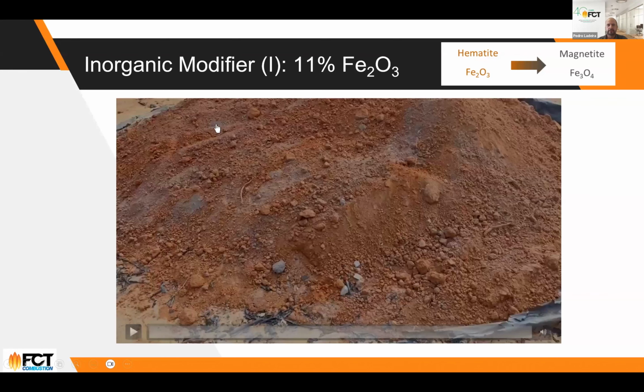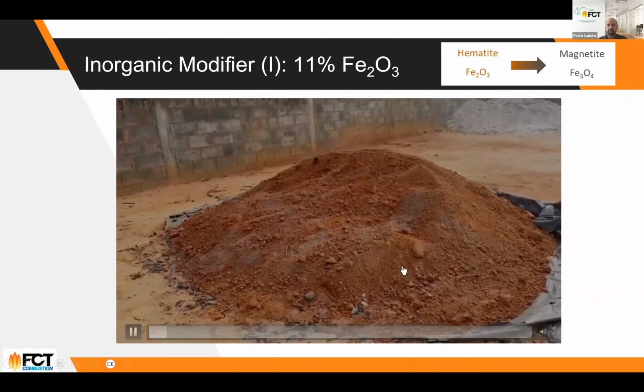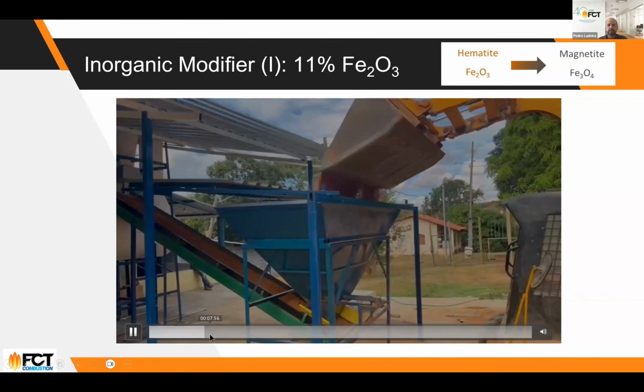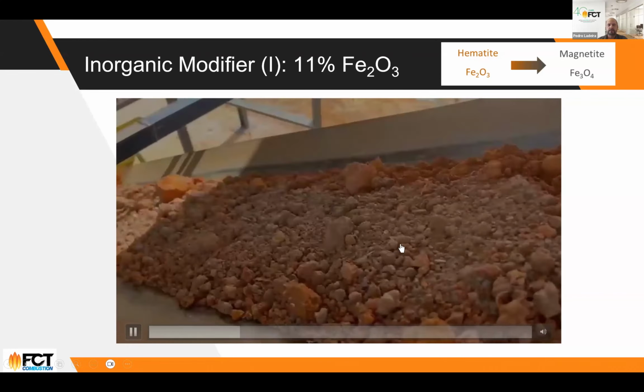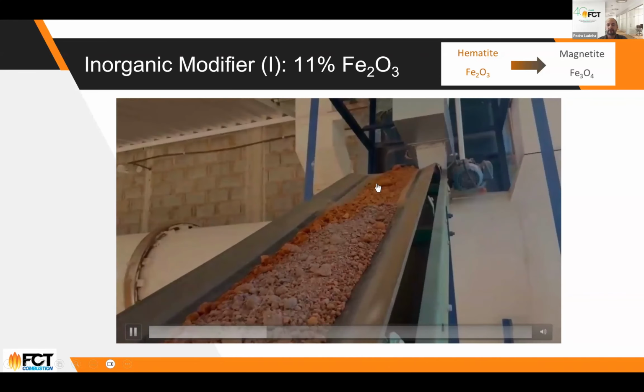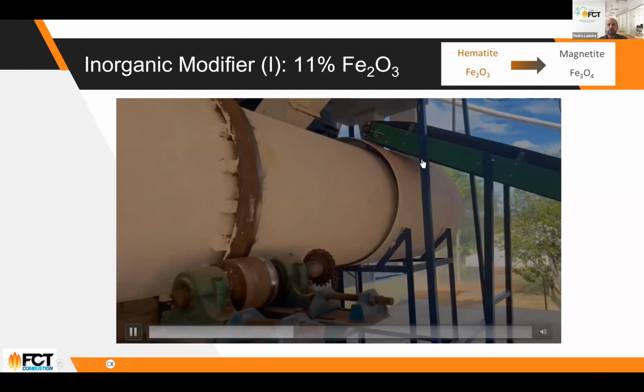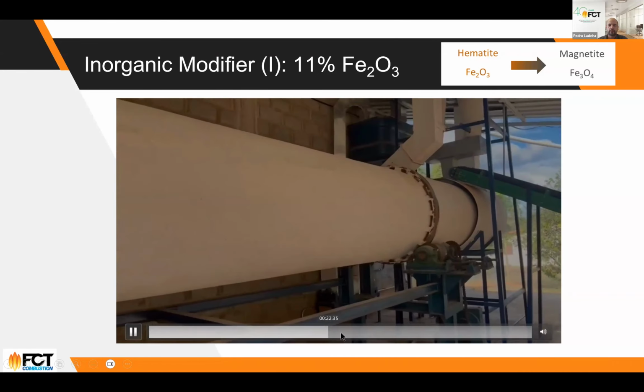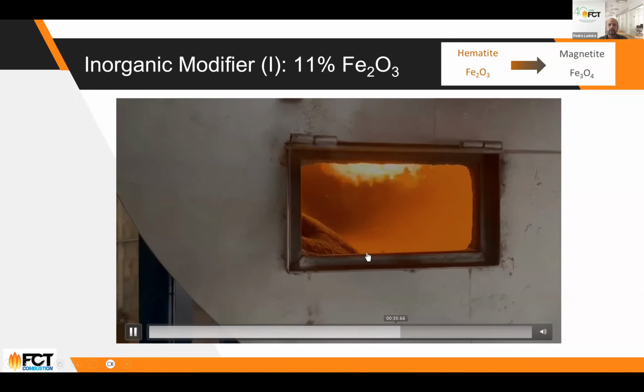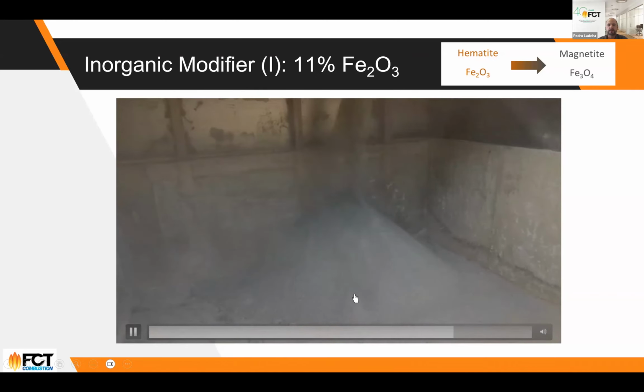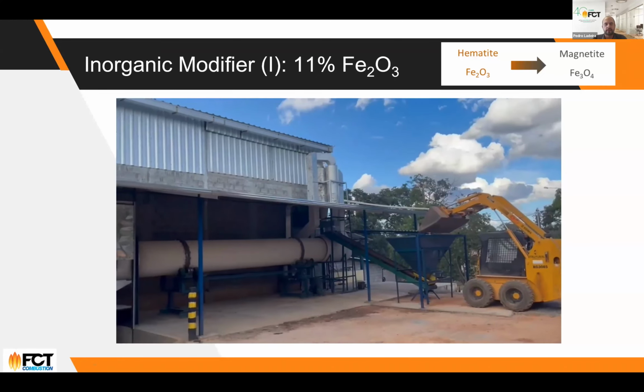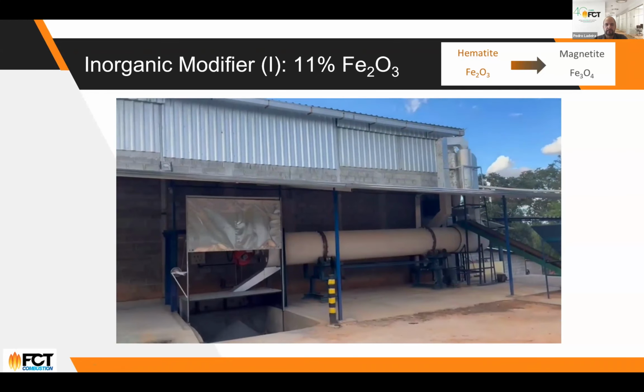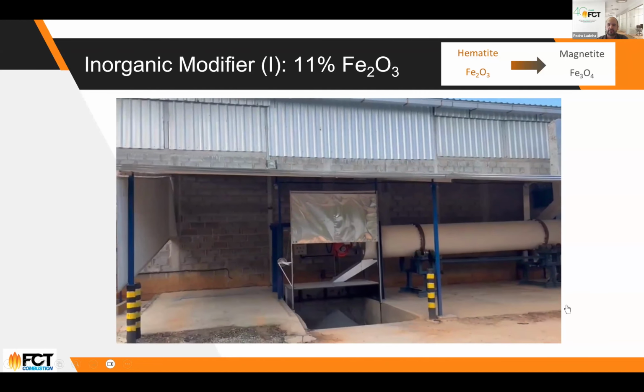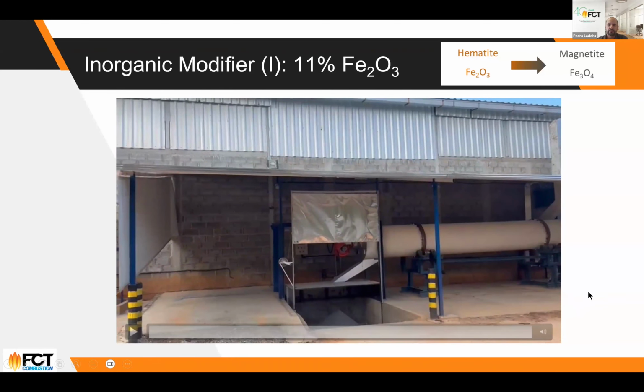So just giving an example, imagine that you have such a red raw clay, and then you start adding a source of calcium to it and submit it to a pilot test. You can see they are mixed together, but they don't have to be interground. So you just co-feed them to a rotary kiln. What you get from this is a product that, without specifically controlling the atmosphere or anything like that, you get a gray color. This test was made in a facility that we have, a pilot plant in Brazil for clay calcination. And so this is the result.